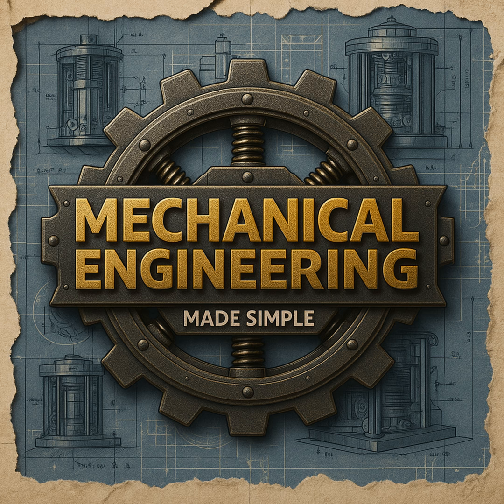And aluminum's real superpowers are its manufacturing agility. It's incredibly easy to machine, extrude, and form, and it has a great strength-to-weight ratio. It's very easy to work with. But the physical property that always blows my mind is its cryogenic performance. Most metals, particularly standard body-centered cubic carbon steel, have a ductile to brittle transition temperature. Right, they get brittle in the cold. You take standard steel, freeze it in liquid nitrogen, hit it with a hammer, and it doesn't dent. It shatters like a glass window. Which, historically, is exactly what happened to the low-grade steel hull of the Titanic in the freezing Atlantic waters. Yes, a classic example of low-temperature embrittlement.